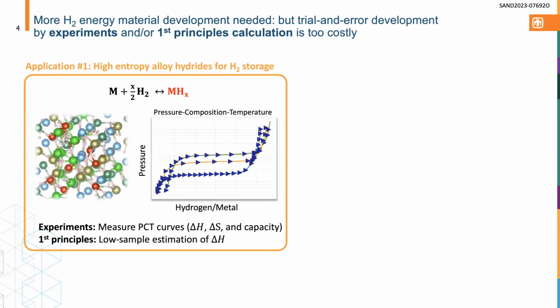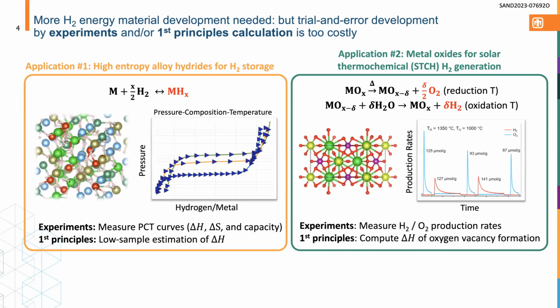Next. So we need to do a lot more materials development for these hydrogen energy materials, but the problem is that experiments and first principles calculations are pretty costly. So I'll talk about two applications today. Generally, metal hydrides, you expose them to hydrogen environment and they go through some kind of phase transition, allows you to absorb a lot of hydrogen at a set pressure. Experimentally, we can measure these and back out the thermodynamics. But from first principles, typically what people just do is look at things like a low sample estimation of the